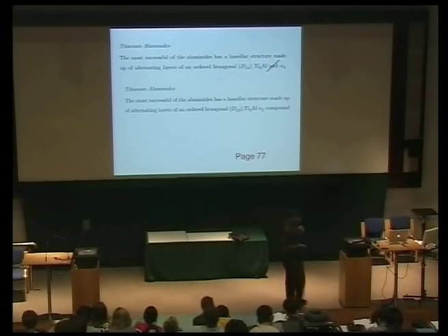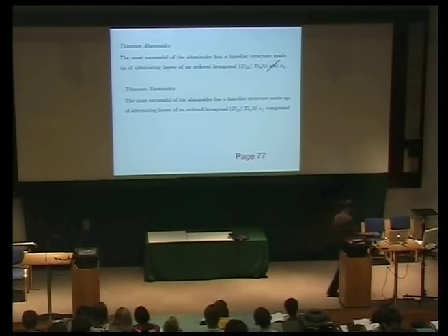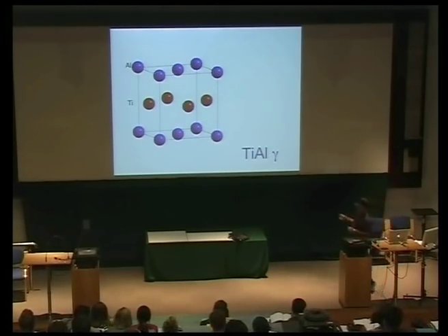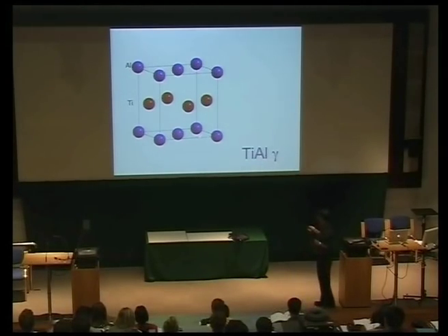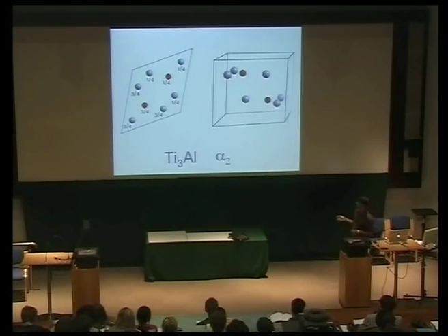And in the titanium system, there are two interesting intermetallic compounds. The first one is an ordered hexagonal phase, Ti3Al, which we call alpha 2. And the other one is the TiAl gamma, which has a structure like this. Again, you don't need to remember anything about this particular crystal structure. It's a particular crystal structure of titanium aluminide. This is actually tetragonal, and you can see that it's an ordered phase. So this is TiAl in the gamma structure, and a more complicated ordered hexagonal Ti3Al alpha 2.